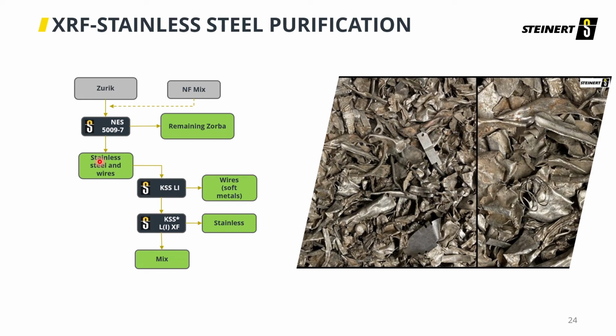So in general, you could use the KSS with a laser and induction sensor to eject out your soft metals, generally your wires. Maybe this is an in-feed for a granulator line, a chopping line, etc. And then you take that predominantly stainless fraction into your KSS XF, and it's going to upgrade your stainless percentage. Based off your in-feed concentrate and the in-feed product to this process, it may not look exactly like this, but effectively, based on that in-feed to the XF, you can see a high upgrade in stainless steel percentage. In some instances, with a solid in-feed and a good pass over the XF, we've seen 99% plus stainless.